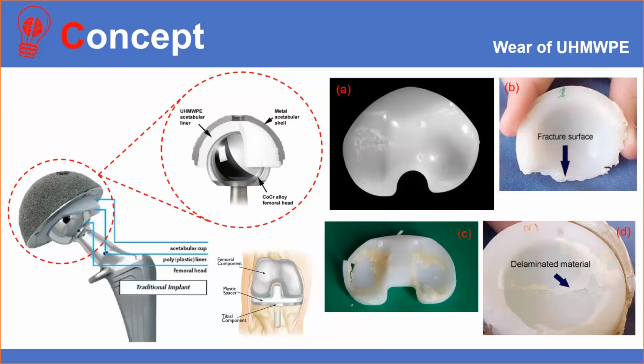So orthopedic components must undergo sterilization before clinical use. When ultra-high molecular weight PE is exposed to a stronger energy than that of the chemical bond, the consequence is bond scission and the formation of free radicals. This fragmentation modifies the mechanical properties of the polymer itself. Being exposed to high energy gamma radiation during this sterilization process can have a detrimental effect on the morphology and mechanical properties of ultra-high molecular weight PE due to the continuing chain scission and long-term oxidative degradation.